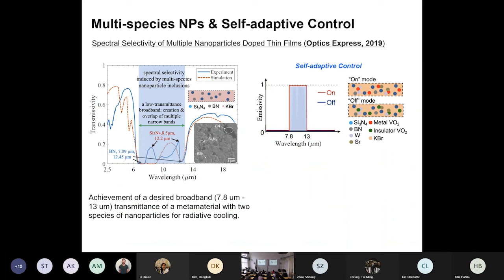We also try to add two other species, tungsten (W) and strontium particles. With the inclusion of tungsten and strontium particles into vanadium dioxide, we are able to lower the phase change temperature down to room temperature. Because the original phase change temperature of VO2 is 68 degrees C, 341 Kelvin.